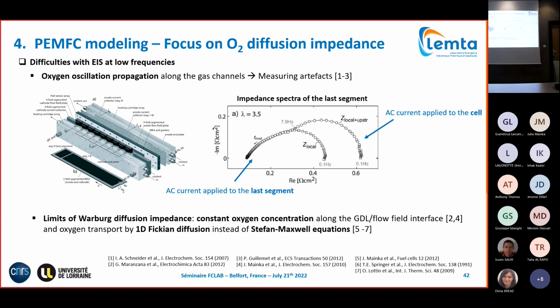The difference is that if you apply a current perturbation, higher or lower current means higher or lower oxygen concentration, so you apply oxygen concentration perturbations, and in a linear cell they will propagate along the cell and perturb your signal, creating artifacts. So it's very tricky to separate what is an artifact and what is real physics of your cell. Another point is that the Warburg diffusion impedance assumes constant oxygen concentration along all the flow plates and is based on one-dimensional pure diffusion instead of Stefan-Maxwell equations.